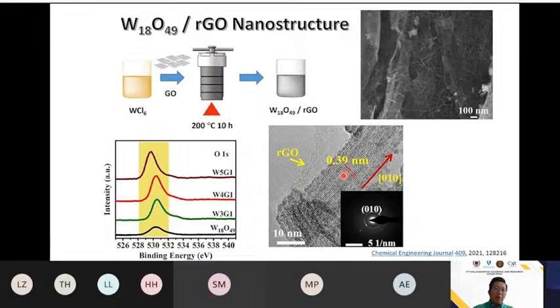And because the performance of the previous one is not really good, we tried to find out if there is any other way we can improve it. So we incorporate graphene into the structure of this tungsten oxide. During the synthesis process, we add in the graphene oxide. Then we find that the tungsten oxide is successfully grown onto this graphene oxide sheet, reduced graphene oxide sheet.